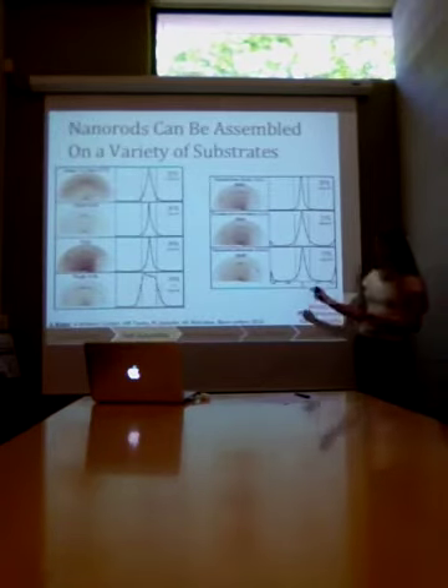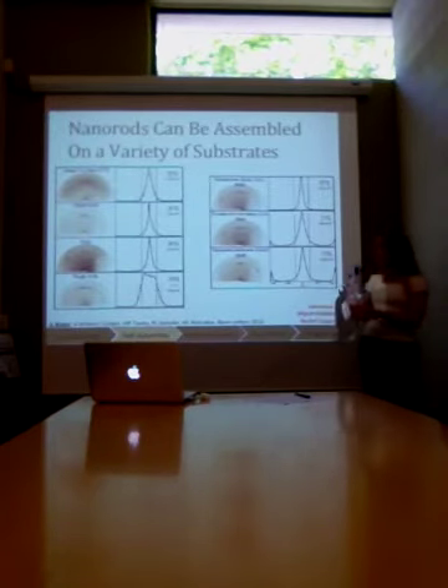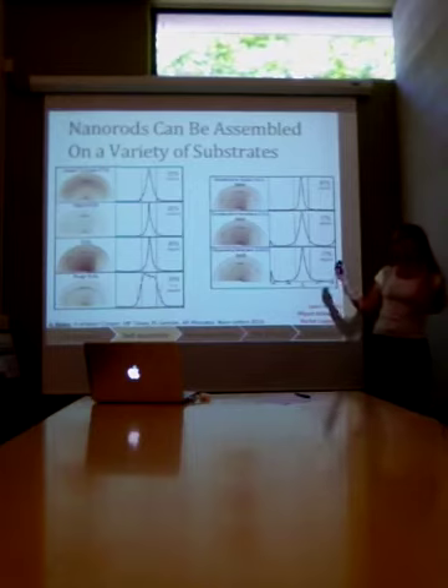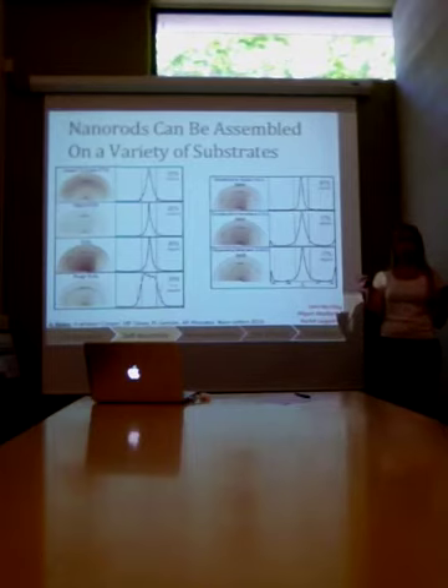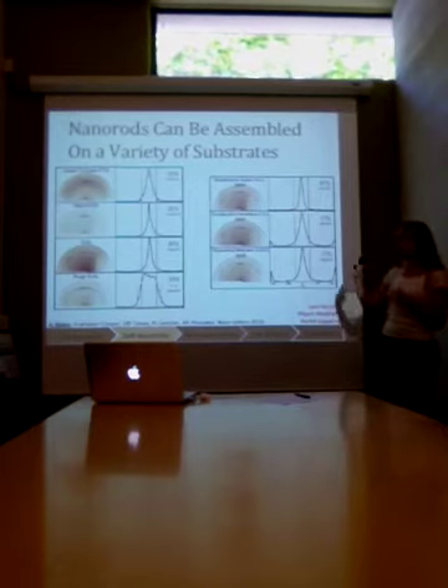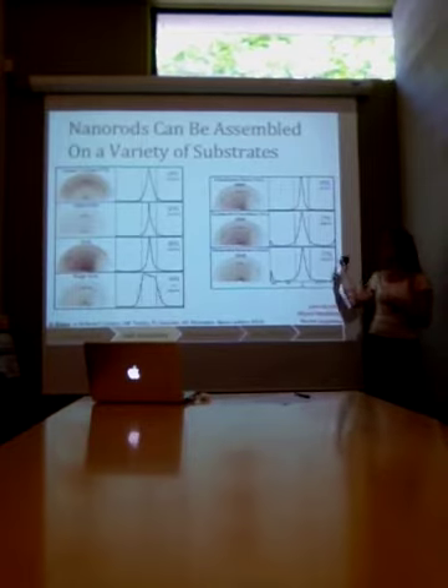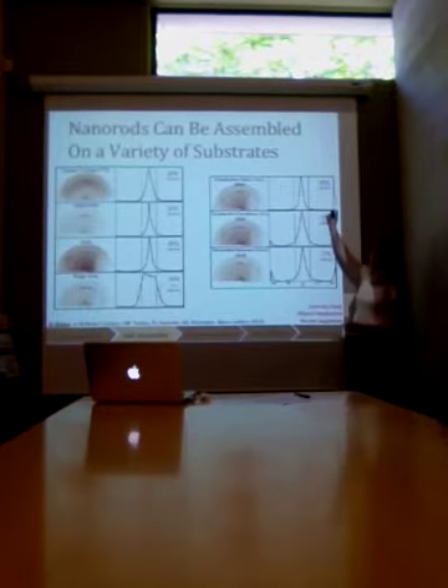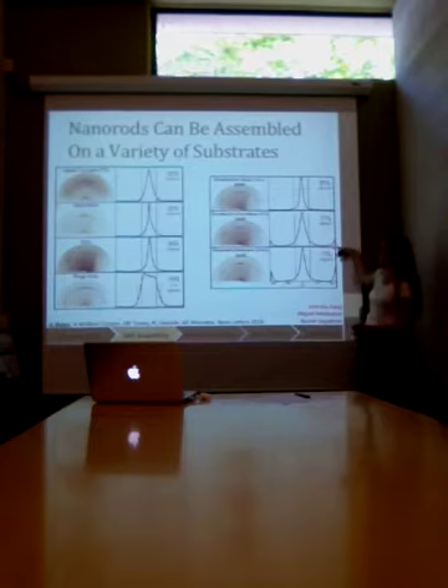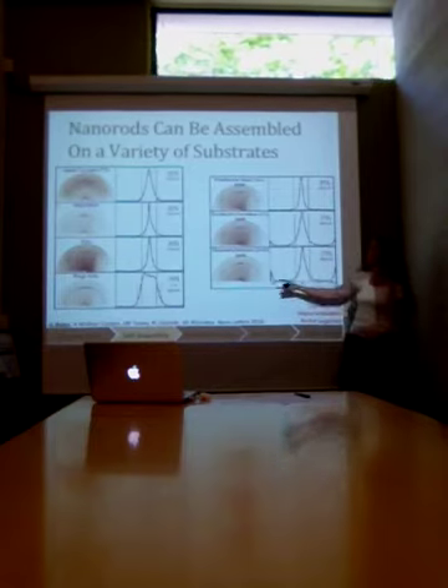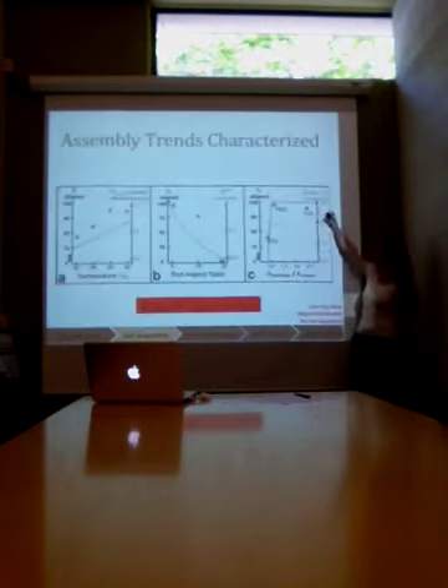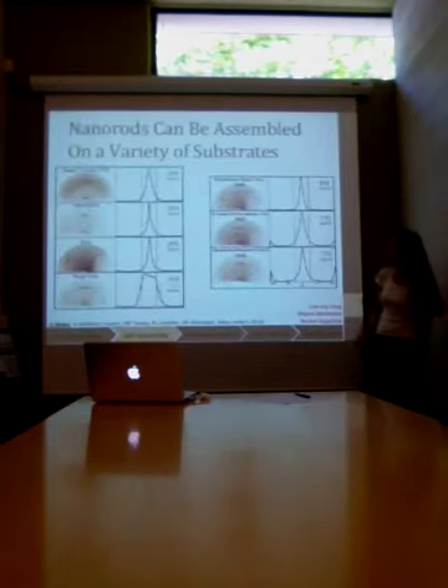Using this technique, we went back to our nanorod alignment and we tried to look at which types of substrates we could align on. And we found we could align on a variety of device-relevant substrates. But some of the alignment was much better than others. You can see these peaks indicating rods are laying down on this one, and you don't see any rods laying down on some of these substrates.